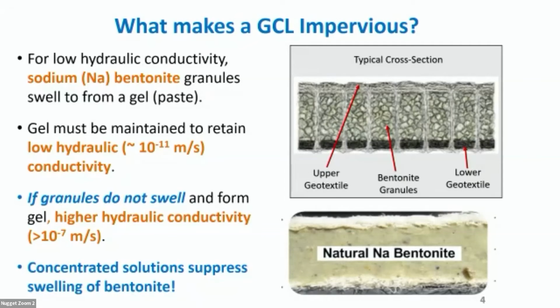It may become very impermeable, like this one that I exhumed from a site in the Sonoran Desert. This had been in service for about a decade, still very impermeable, about 10 to the minus 11 meters per second. But in some cases, we'll have applications where those granules don't swell at all. And it will be very, very permeable and an ineffective barrier.